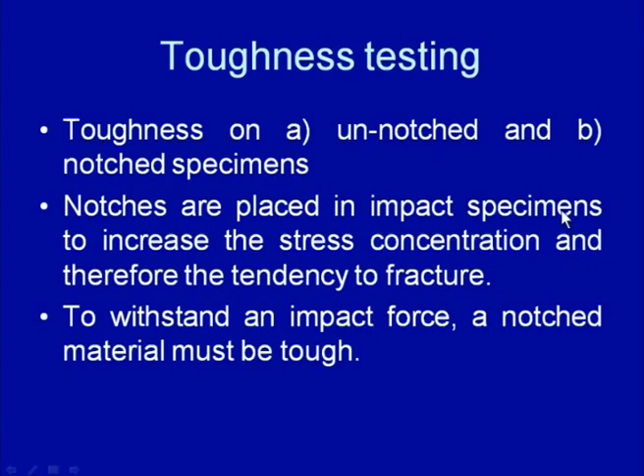Since the presence of a notch increases the tendency of the material to fail, especially under impact load conditions, that is why notch toughness becomes a more useful way of assessing the toughness of the material. So, the notches are placed in the impact specimens to increase the stress concentration, and with the presence of those notches, the tendency of the material to resist the fracture under the impact load condition is assessed.